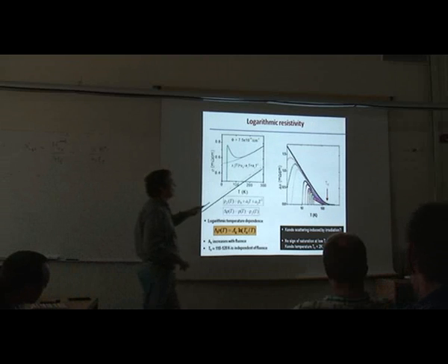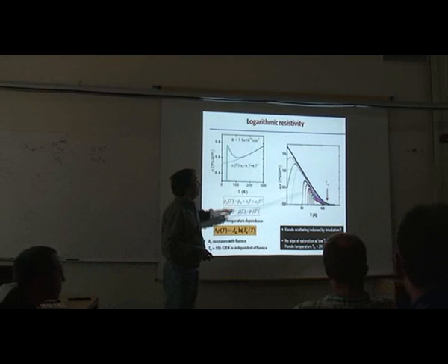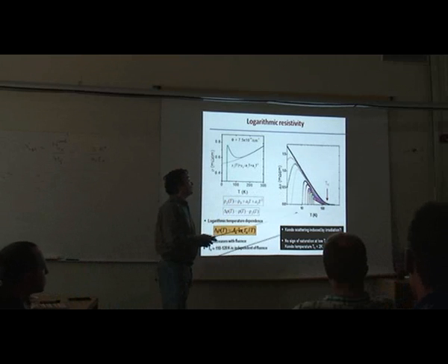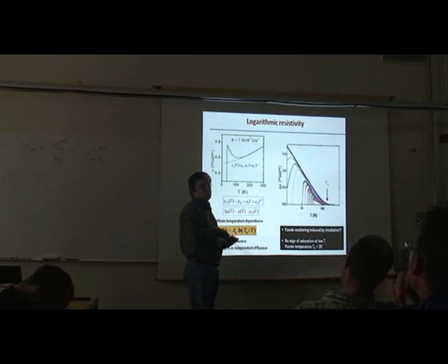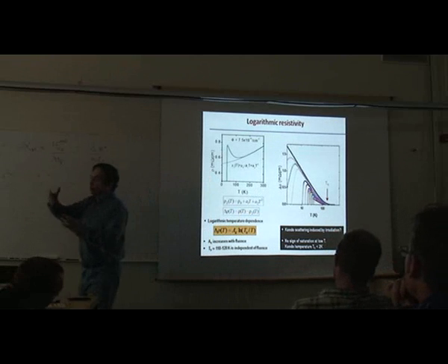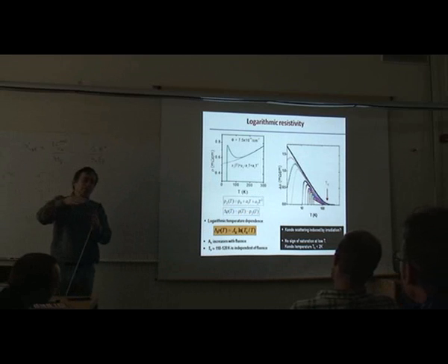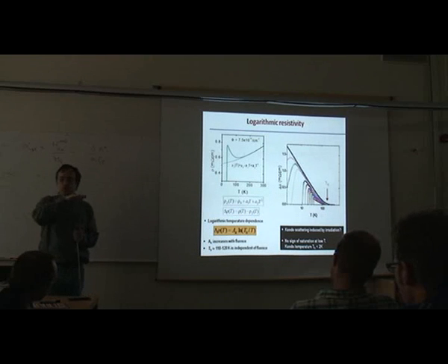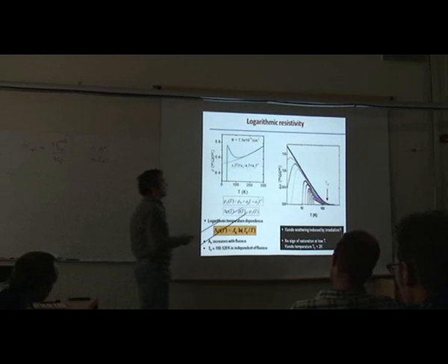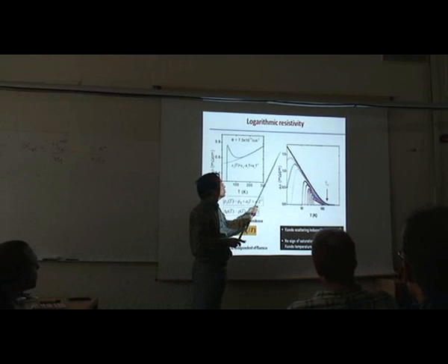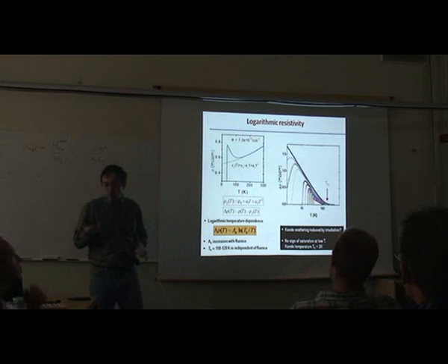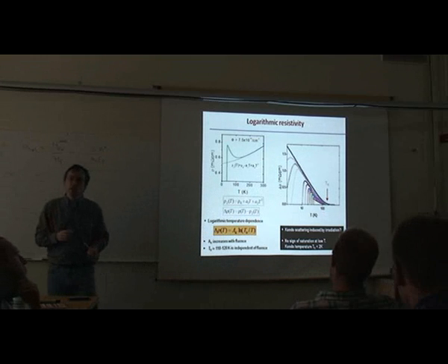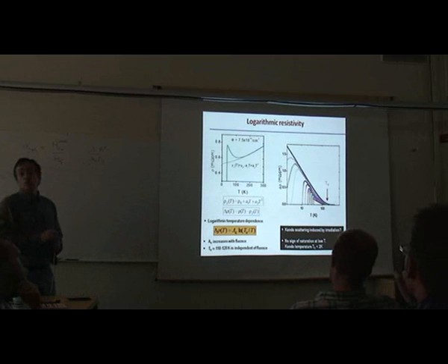However, something is unusual about this Kondo interpretation too, because usually in Kondo systems, at very low temperatures, there's always a saturation, because when magnetic moments form the bound state near the impurity, it cuts off the logarithmic divergence in resistivity. So here we can go down to 2 Kelvin and see no sign of saturation, so we can only speculate that probably in this system the Kondo temperature is below 2 Kelvin. Is it a spin 1/2 impurity? We don't know.